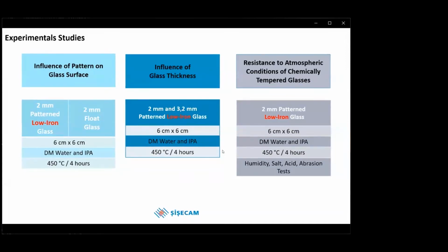In the second part, where we examine the effect of thickness, we will compare 2 and 3.2 mm patterned glasses in terms of chemical tempering behavior. In the last part, the resistance of chemically tempered patterned glasses to atmospheric conditions such as humidity, salt, acid, and abrasion was examined.